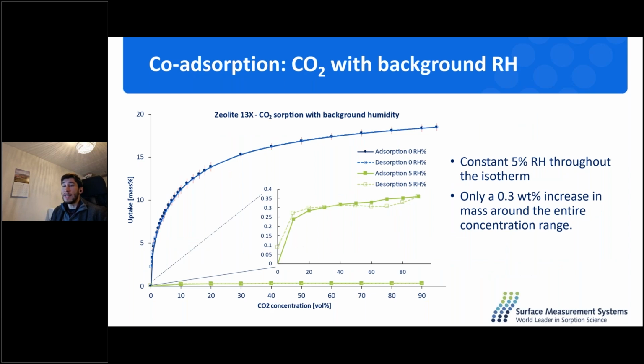Unfortunately, water has a negative impact. So this isotherm here at the bottom, you can see it, is recorded with a constant 5% RH throughout the entire isotherm. So this was recorded in the DVS carbon with a constant background relative humidity of 5%. And then afterwards, putting CO2 in at these concentrations. What we see is that the uptake compared to the original isotherm, when CO2 is put in, seems minimal. It's 0.3 weight percent compared to 15 to 20%. So it seems that CO2 does not adsorb on top. But as we've seen, it's a little bit more complicated than that.